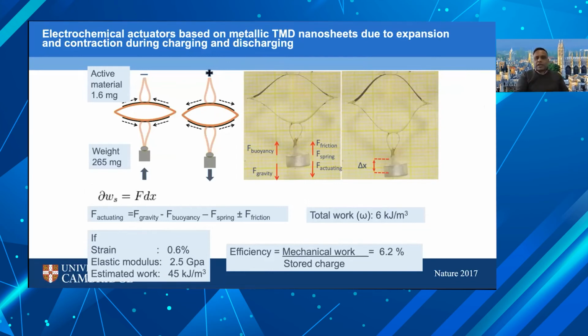So my student designed this bimorph actuator without any moving parts. He took a strip of polyimide and made some strategic cuts and put MoS2 film in specific locations such that upon intercalation and deintercalation, the top layer would contract this way, the bottom layer would contract this way. And this way, the actuator is able to expand and contract.